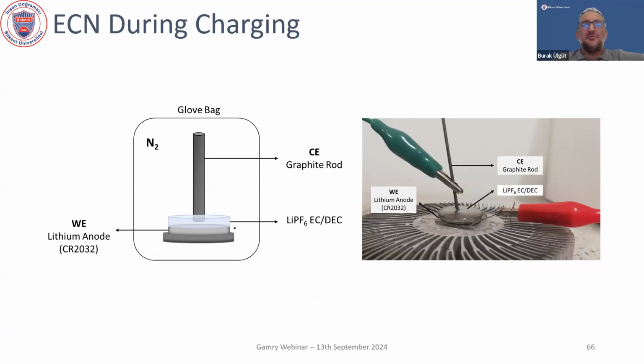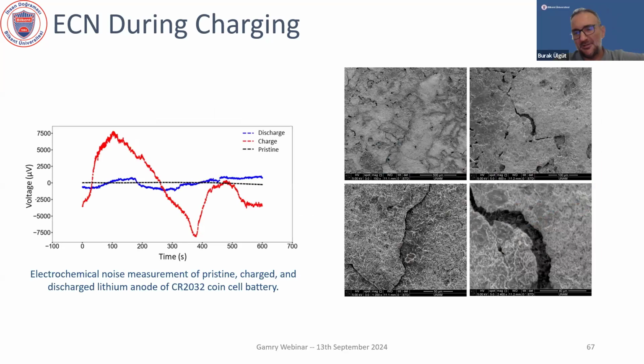Now, what we have been struggling with for the past few years, and we are pretty excited about this, but it's a hard experiment to do, is during charging. Because if you think about one of the bigger problems in batteries and electric vehicles, it is fast charge. The problem with fast charge is there are two competing reactions. One of them is intercalation of lithium, the other one is plating of lithium. And if it plates, you lose capacity. If it intercalates, everything is fine. We believe, and we have some pretty early indications in our preliminary testing, that plating actually adds a significant amount of noise, as you can see here, whereas intercalation does not generate noise.